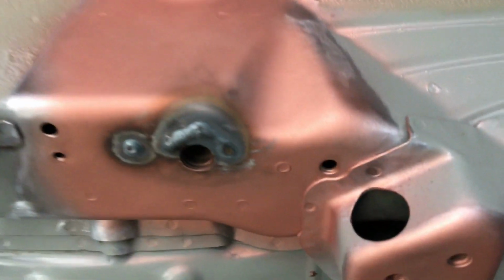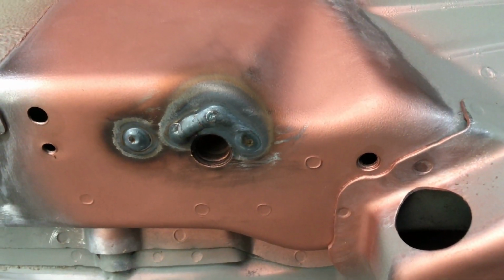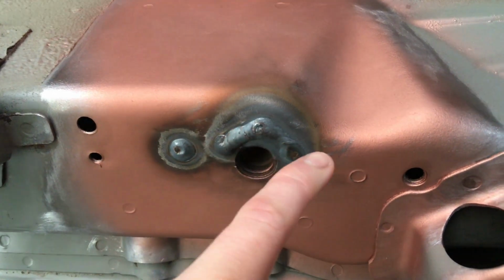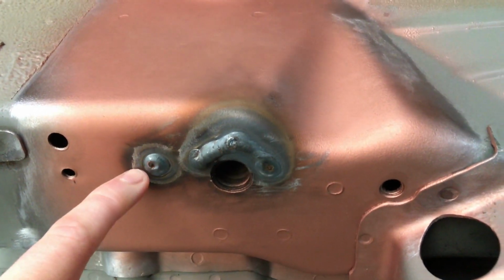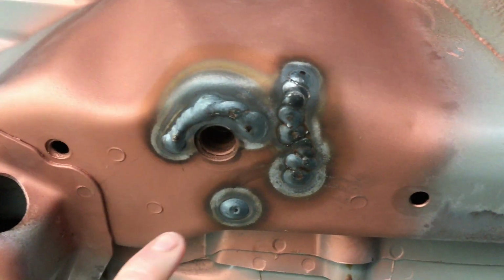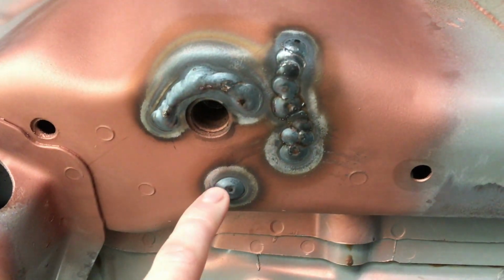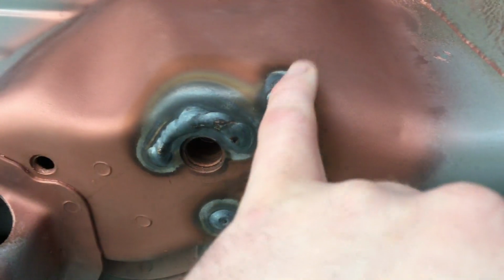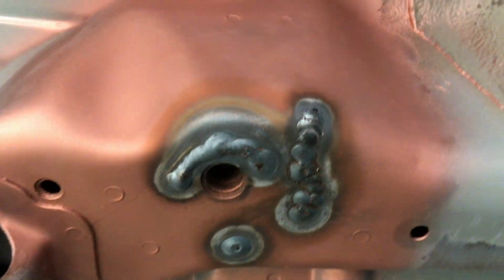We finished welding the cracks that we found and the broken spot welds earlier on. I'll just show these before we start grinding them down. So that's the left front mount where we have the semicircle crack and we cut a channel out, and there's one plug weld which replaces a spot weld. Then on the right front we've got the semicircle crack repaired there, one spot weld, another spot weld, and the crack that we opened, stop drilled earlier on in the process.